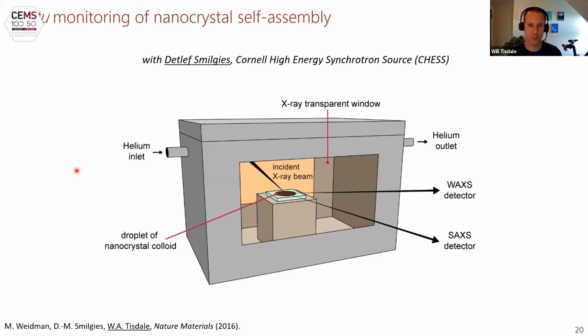The experiment my student Mark did is he took a droplet of the colloidal suspension of lead sulfide quantum dots in toluene. He dropped it on a smooth silicon surface. He put a few extra drops of toluene in the chamber so that there would be appreciable toluene vapor pressure. He closed up the chamber, he closed up the X-ray safety doors, and he walked out. And then he started simultaneously collecting small angle scattering patterns and wide angle X-ray scattering patterns while he flowed a helium carrier gas through the chamber to slowly dry out that droplet and watch the superlattice form. And here is the data he collected.